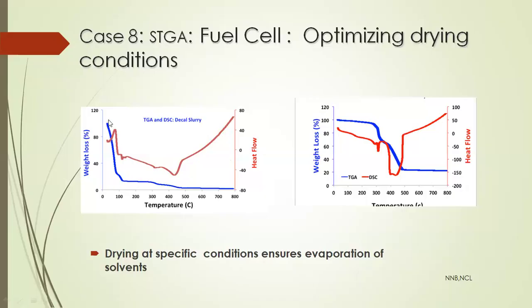And I told you that this could be because of the water, because of the organic solvents. So our drying condition of the electrodes was not proper, which was revealed by the TGA. And when we modified the drying conditions and drying time, this electrode gave us a beautiful current density. And you can see here that up to 300 degrees centigrade, there is absolutely no weight loss, or a small weight loss, which is acceptable for fuel cell condition.